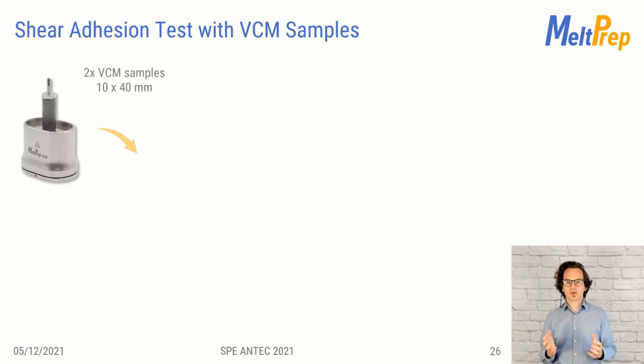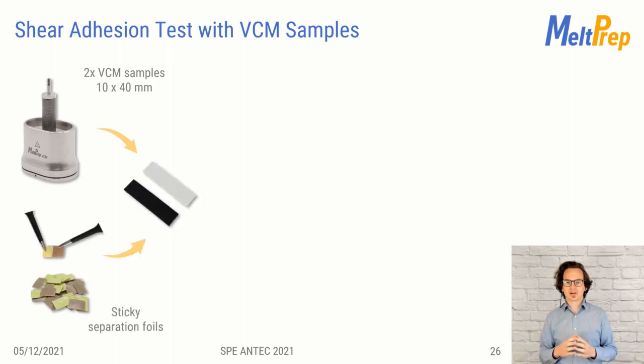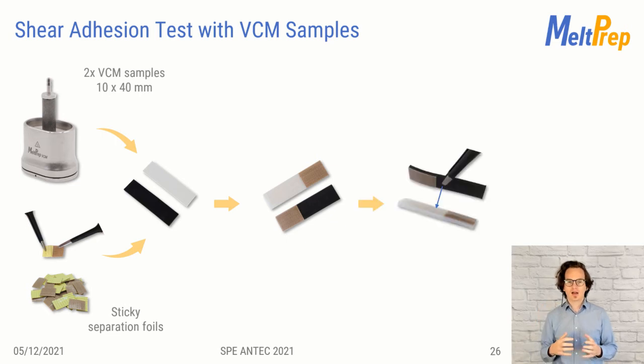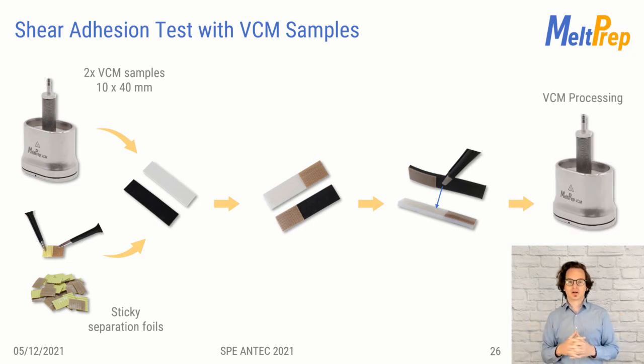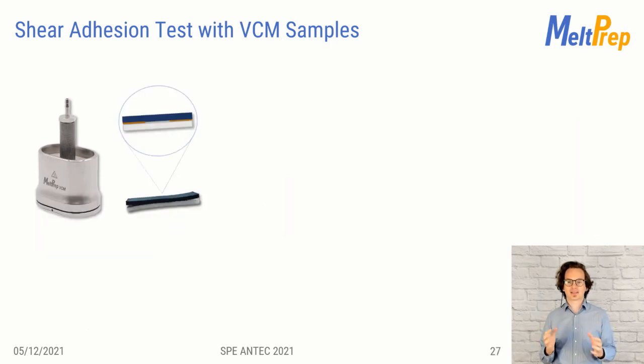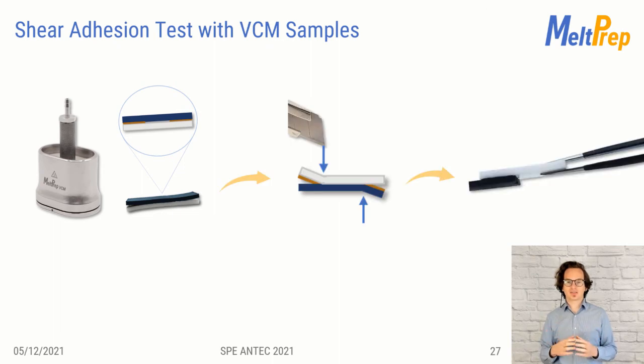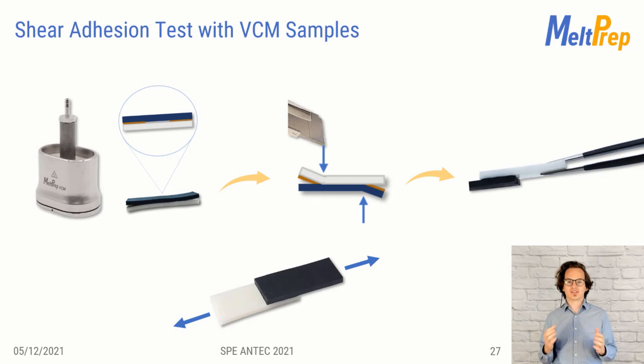For example, if you work with composites or you're interested in interlayer properties, you only need 2 VCM samples out of different materials and some separation foils that have pressure-sensitive adhesives on one side. Place one foil on each sample, place them into the VCM tool. After one processing cycle, you fuse them in a defined area, in our case 1 by 1 centimeter, cut the parts with the foils and receive an excellent sample for a shear adhesion test, for example.